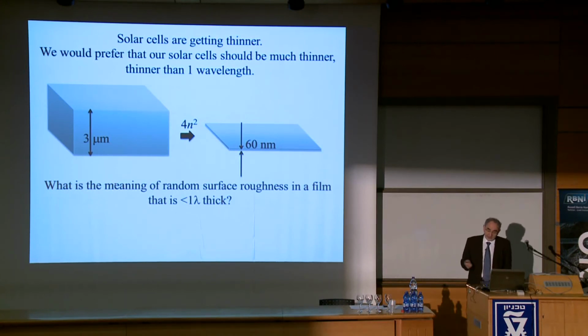And I'll try to be practical about it. Suppose you have a good direct gap semiconductor like gallium arsenide. 3 microns is more than enough to make a good solar cell. Now, if you use this light trapping factor, that means the film is going to be very thin. It could be 50 times thinner, so this would be only 60 nanometers thick. Obviously, that's much less than a wavelength, and so you can't use a geometrical optics argument.